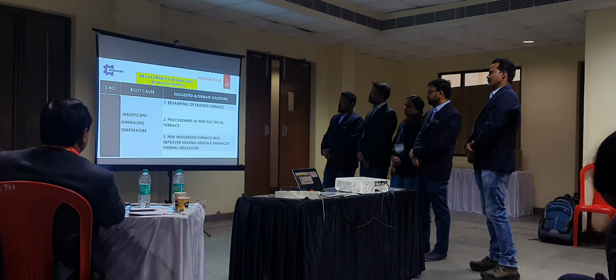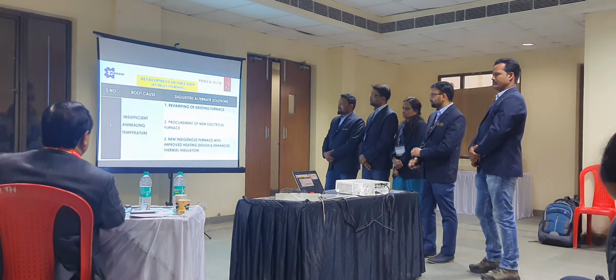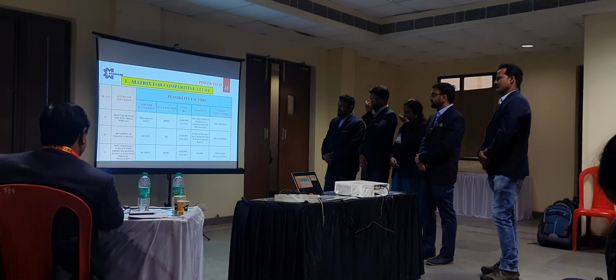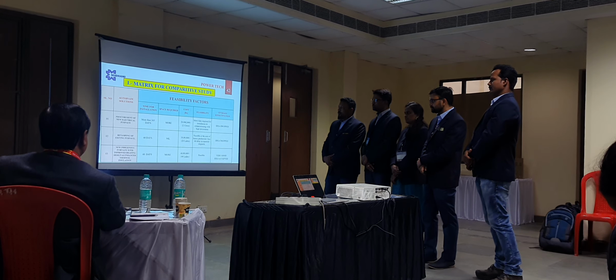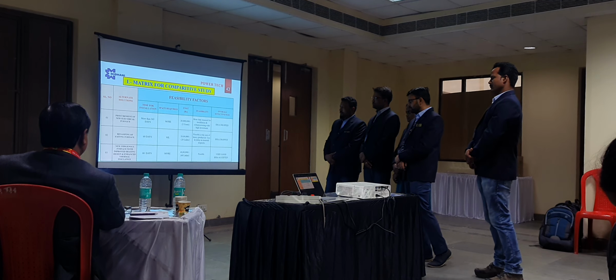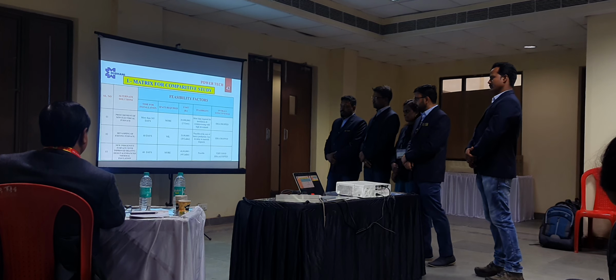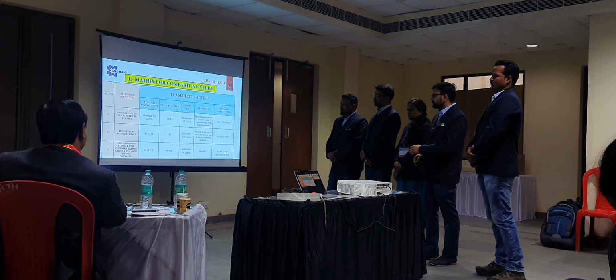In Step 4, Improve, we conducted many brainstorming sessions for development of solutions, where our team members suggested 3 alternate solutions for the root cause. And we prepared the L matrix for comparative study to check the feasibility factors. What is the first alternate solution? Procurement of a new electrical furnace. It requires more than 365 days for installation, with a cost of investment of 2 crore. As the time and money involved are very high in this case, we found the feasibility factor very low, and this idea was dropped by our team members.